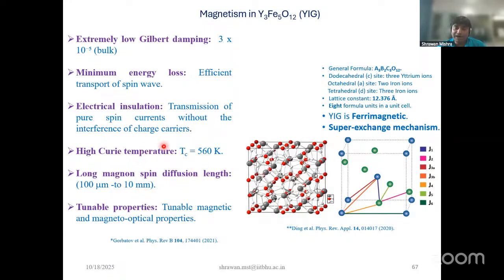So if the ordering temperature of the material is above room temperature, only then can you make any conceptualization of making devices. And the thing that is more important for this material is a long magnon spin diffusion length. It's from some hundreds of microns to 10 millimeters. That's very significant. So a spin wave can travel 10 millimeters without any dissipation. That's a unique ability of this garnet film.